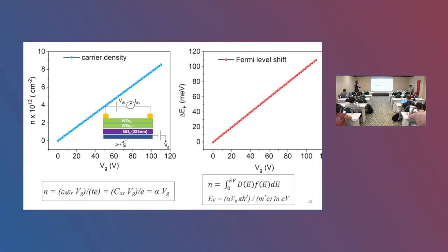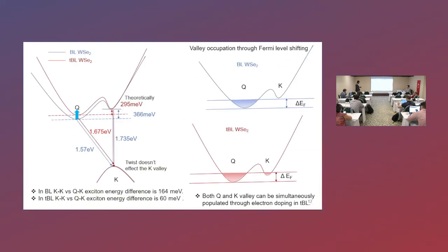And we can clearly see that our limit is that we can push the gate voltage to 100 volts. After that, it will start leaking. So we can't go above that, okay? Up to 100 volts is almost similar to a 110 millielectron volt Fermi level shift. And if we go back, we can clearly see that the distance between them is around 200 meV. That is larger than the overall shift. That's why we are not able to probe the simultaneous valley. But for the twisted bilayer case,